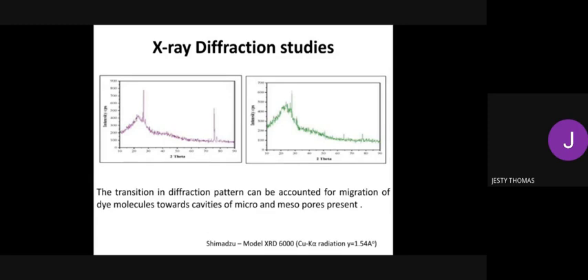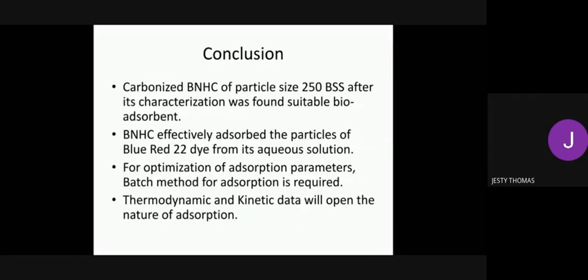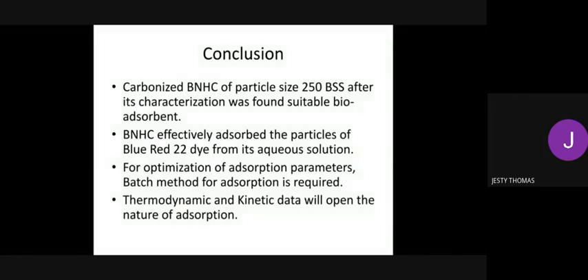Now we recorded X-ray diffraction also. Some differences are noticed in the changing peaks, and these were because of the adsorption of the dye molecules. The XRD showed that these particles are crystalline in nature, and we noticed 2 theta values of 20, 21, 23, and 26 at the respective positions. So we recorded FTIR, XRD, and SEM images.